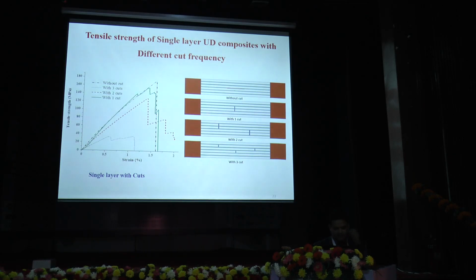You can see that when we increased the number of cuts in a single layer, we got enhanced ductility, but only up to 2 cut discontinuities. As we introduced 3 cuts in the same specimen, its strength and ductility both reduced. This could be due to the more resin-rich region caused by the discontinuous portion of the fibers.